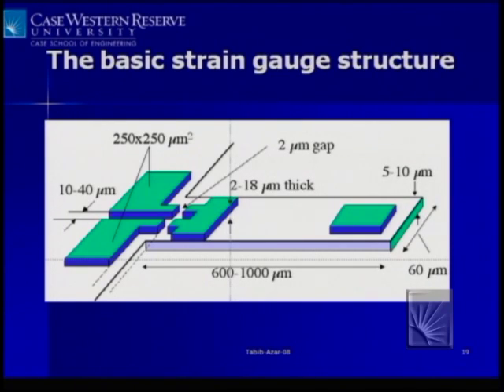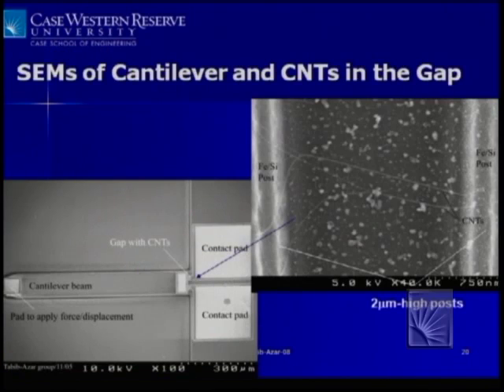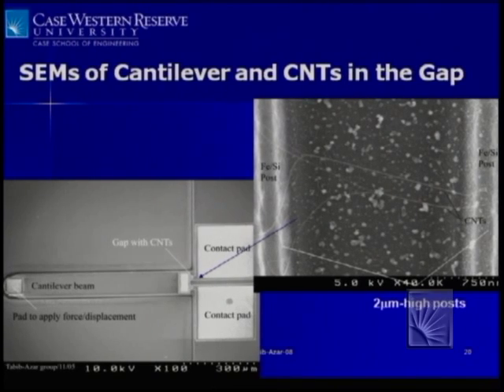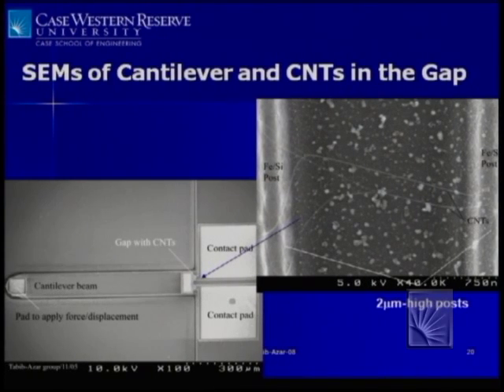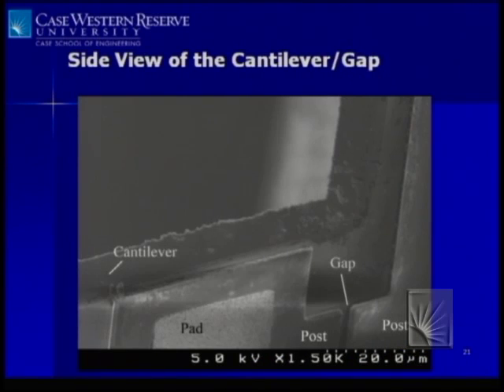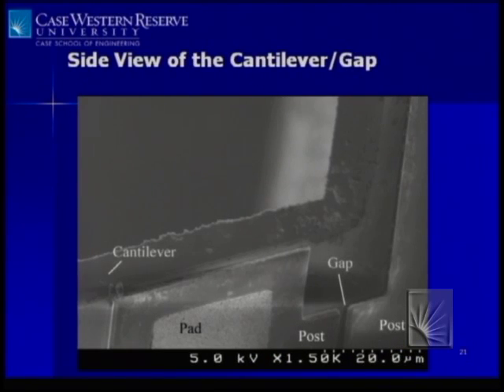So the idea was to use a cantilever beam and put these posts at a strategic location on the neck here. And so when you bend, this gap opens up, and when it opens up, it enables these carbon nanotubes to telescope out or in, and then you can use the current versus voltage characteristics between those 2 posts to see what's happening. So this is an SEM image of the cantilever beam before it was released. This is the SEM image of the gap with carbon nanotubes in there that we grew using the technique that I mentioned. I hope you guys can see this.